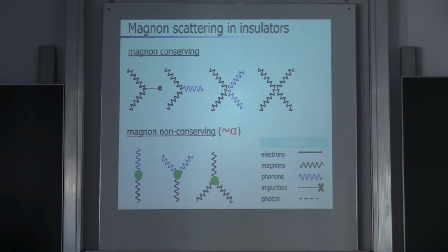Now all these scattering processes involve the spin-orbit interaction, and they are therefore much weaker. It depends, of course, on the material. But we know that in YIG, this damping parameter alpha, which is just the loss of angular momentum, right? The magnetization dynamics is damped, which means angular momentum is lost or gained, as you would like to call it. So in YIG this is somehow related to alpha, and alpha, in this case, is very small. So it's quite safe to say that all these processes are a perturbation. We first consider the other processes in order to find out what happens to a non-equilibrium state, and this one is a correction to that.